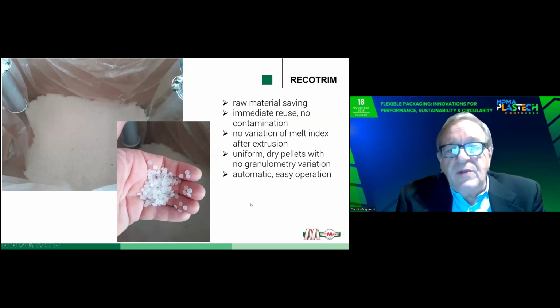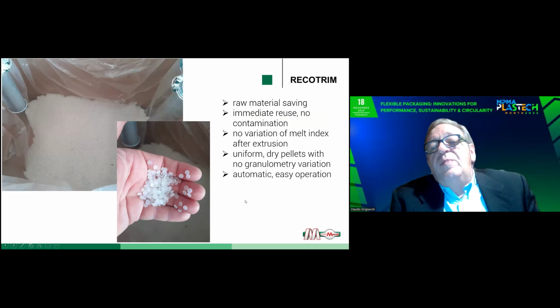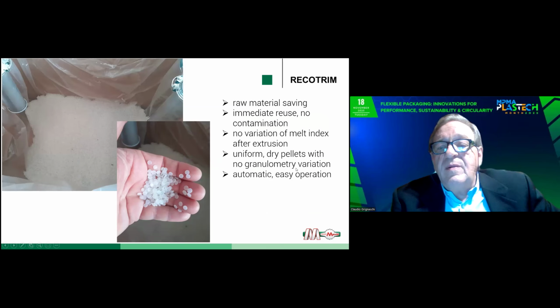And this is what you get. Very clean, high quality, uniform pellets with no granulometric variation. No variation of the melt index after the extrusion, so that you can reuse the pellets immediately without any contamination and refeed them in the central layer of your extrusion line.